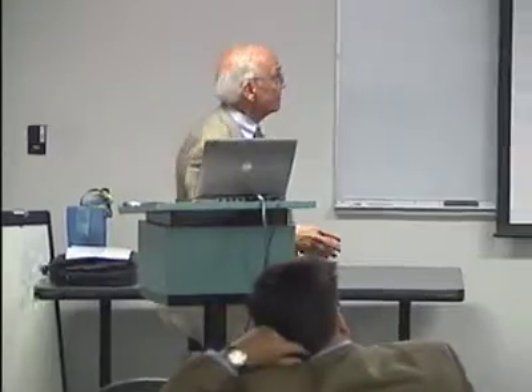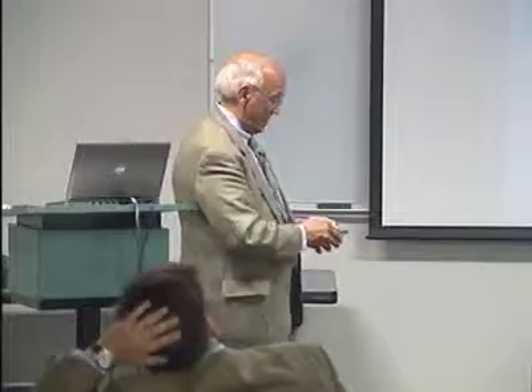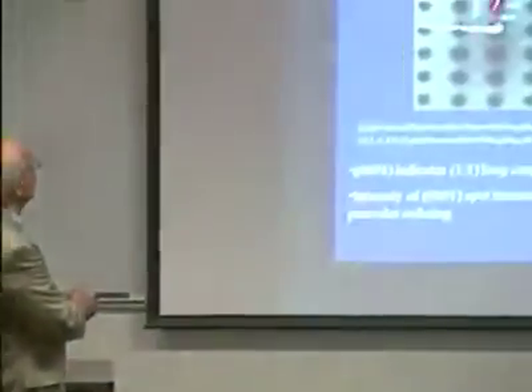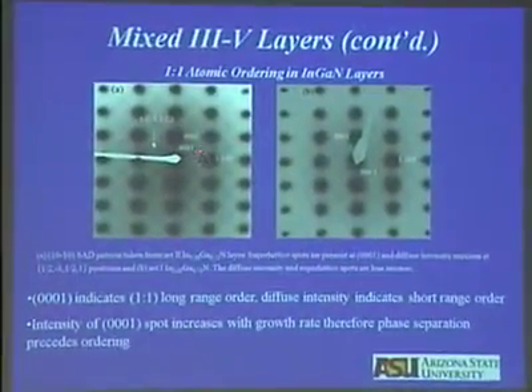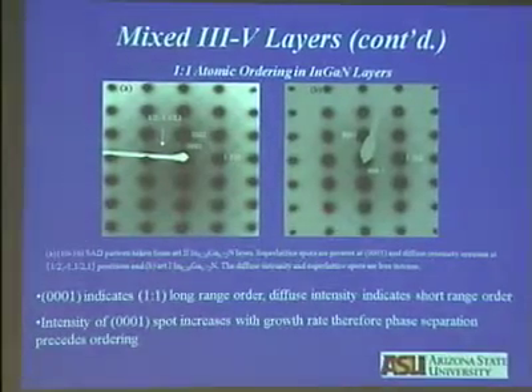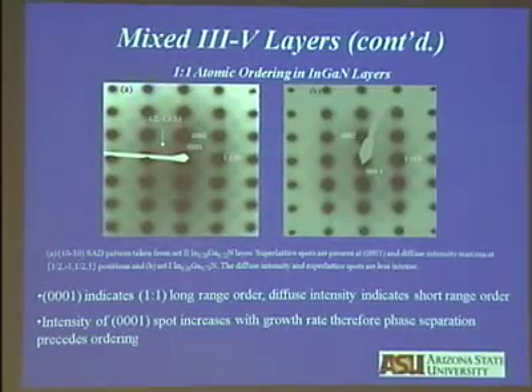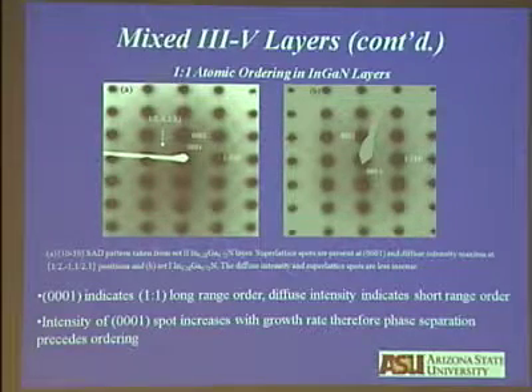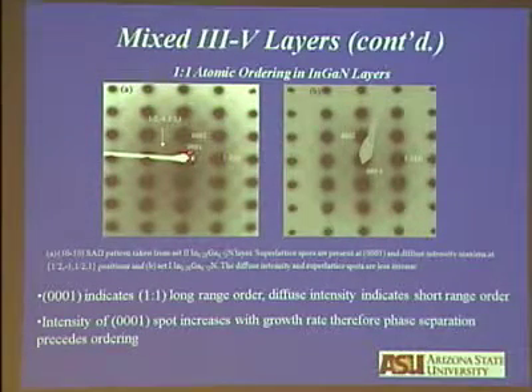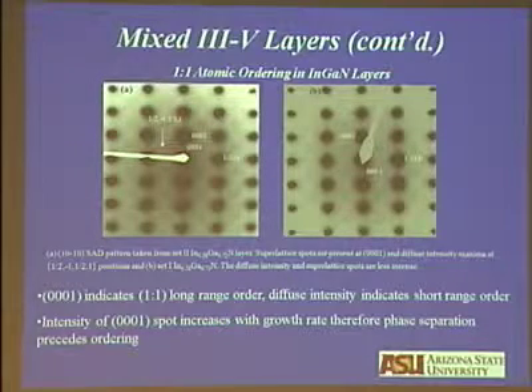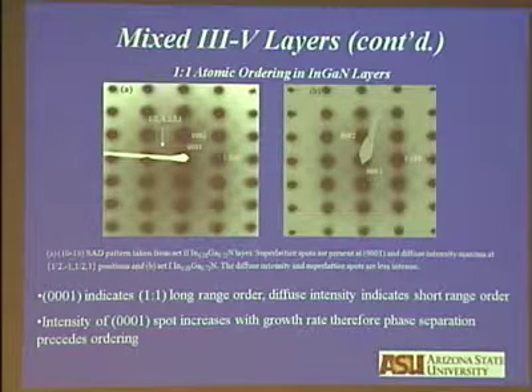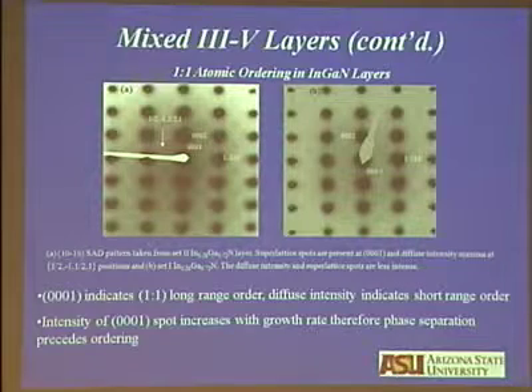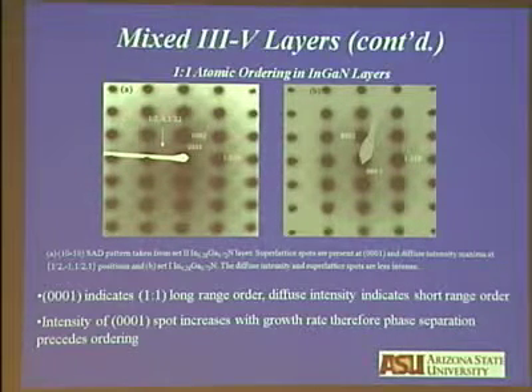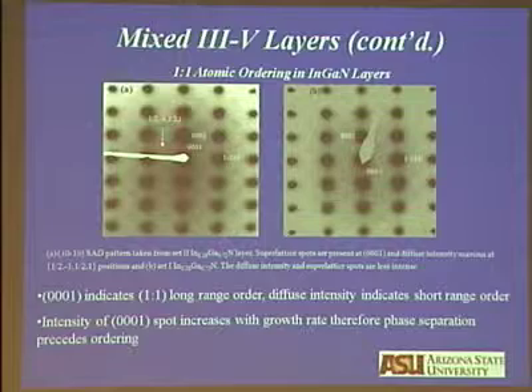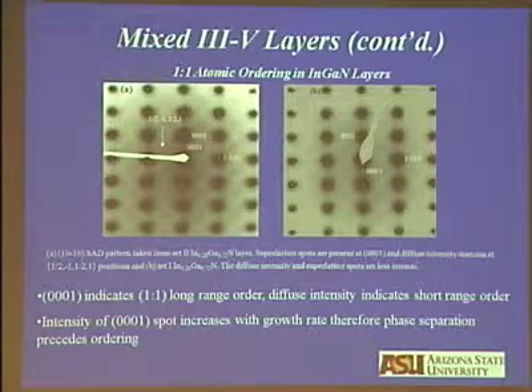Now, just like the 3-5s, the nitrides also order. And the ordering is you get an extra spot at the 0001 position. In the wurtzite structure, in the diffraction pattern, you should not see a 0001 spot. And you see them in indium gallium nitride. Again, the periodicity along the growth direction gets doubled as a result of ordering in these materials. And the intensity depends on the growth rate.